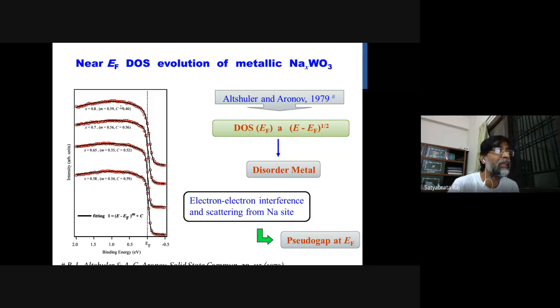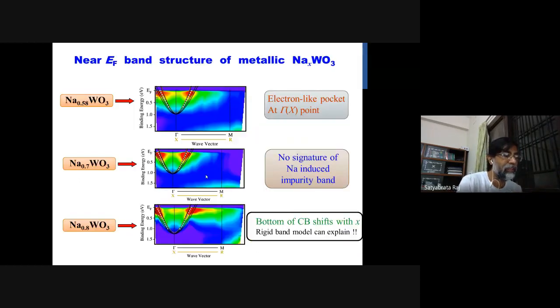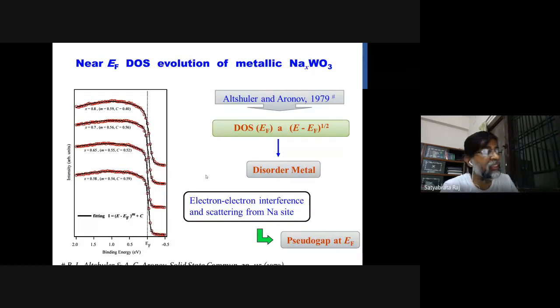But in sodium tungsten bronze, if you measure, you see that there is a cusp-like structure even at very low temperature. That is because this is no more a very good metal, this is a disorder metal, and in the disorder metal the density of states will vary as E to the power half. When the electron is moving, it can interfere and scatter from the sodium sites. That gives a pseudo-gap type of feature at the EF, and that cusp-like structure develops. And this once again validates the Altshuler-Aronov model.